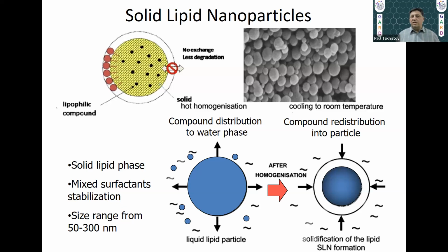So, making nanoparticles. One of the easiest ways is to use the phase transition. For example, solid lipid nanoparticles are widely used in drug delivery applications and also used to deliver nutraceuticals or cosmeceuticals in the food or personal care industry, actually making an emulsion at high temperature and controlling the phase transition during the cooling. And by manipulating the material, you can control the internal structure of these crystals and therefore control the rate of the release.